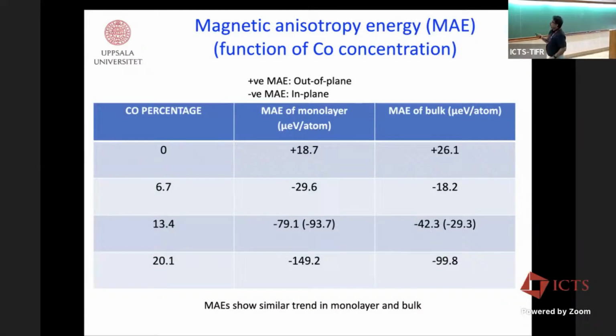Then we calculated the magnetic anisotropy here, the magnetocrystalline anisotropy coming from the spin-orbit coupling. The plus means out of plane, minus is in plane, that's the convention. So if you do not have cobalt here, a pristine system, it is out-of-plane anisotropy as expected. But when you start to dope a little bit of cobalt here, 6.7, 13 or 20%, these three compositions we could do, you see that they have changed to negative numbers. That means the out-of-plane anisotropy has become an in-plane anisotropy.